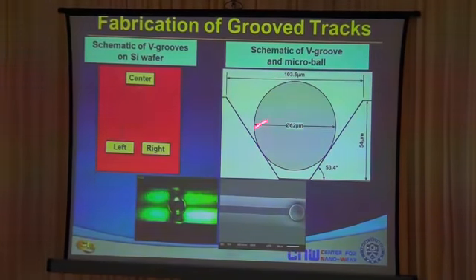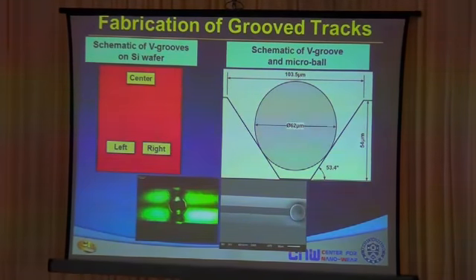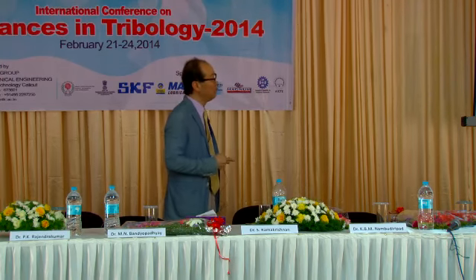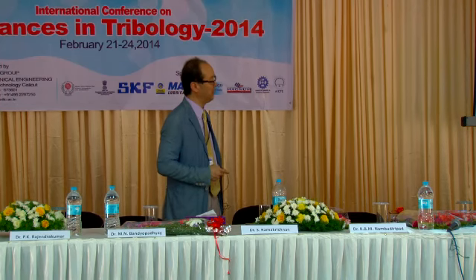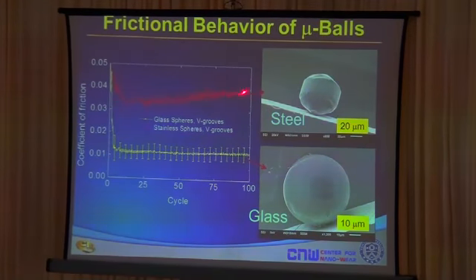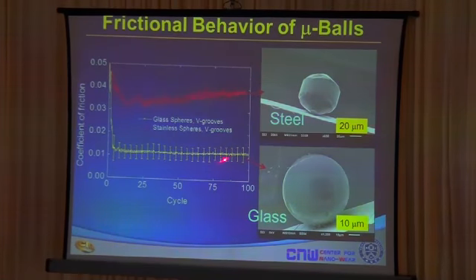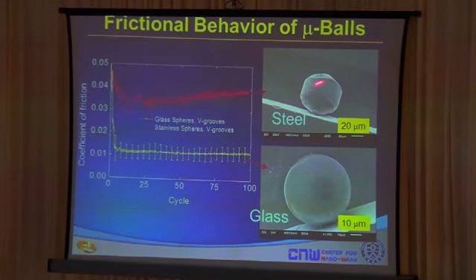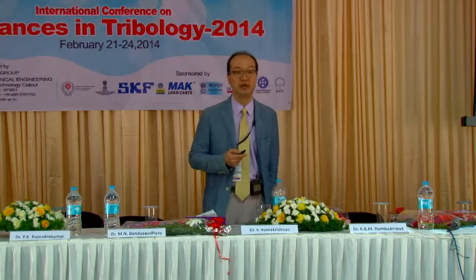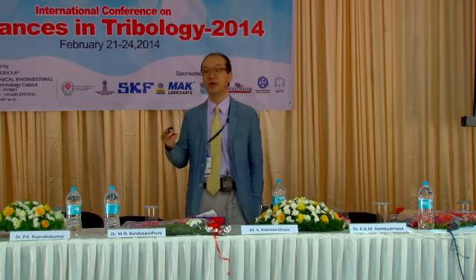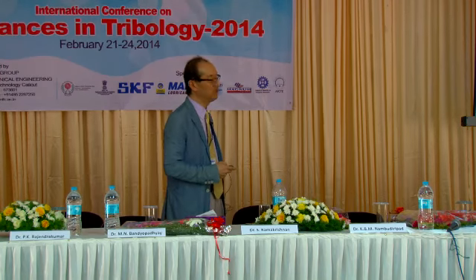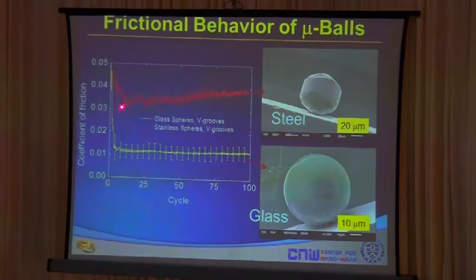And we place our ball inside the grooves, as you see in this SEM image, and also in this optical image. So we have 3 balls inside these grooves, and we put the top surface like this, and we perform our sliding. We use 2 types of balls, a steel ball and a glass ball. That's the friction coefficient of the steel ball, and that's the friction coefficient when we use the glass ball. As you can see, the initially spherical steel ball underwent severe plastic deformation. Now the problem with these micro ball bearings is, unlike macro scale ball bearings, we're unable to heat treat them. So they're in a very soft form, and because of the softness, they undergo severe plastic deformation, and because of that, the friction coefficient is relatively high.